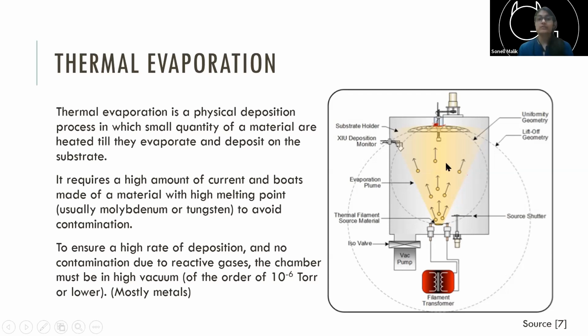So in this process also, you need a very high vacuum of the order of 10 to the power minus 6 torr or lower. That would roughly translate to about 10 to the power minus 9 atmosphere. And it's mostly metals that you deposit this way, because semiconductors usually have much higher temperatures of evaporation. Right. So this was pretty simple. Do you have any questions for this?